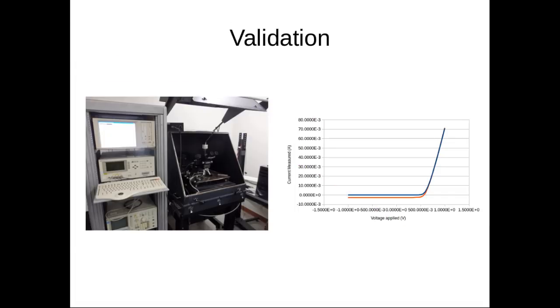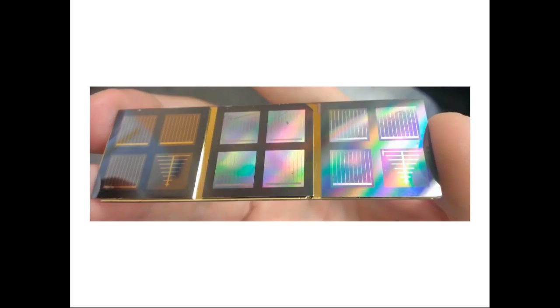Our last processing step is to cut up the devices on this dicing saw. It can be programmed to automatically cut the exact dimensions of your devices. And now we take our devices to the test bench and apply a voltage across the terminals and measure the current. We do that in the complete dark and then with a light applied. And sure enough, we observe that there's extra current produced when there is light applied. So here's our finished device. And that's a 1,000-foot view of how it's made. Obviously, industry scales this process up, and it's all done with robots, but the processing steps are exactly the same.